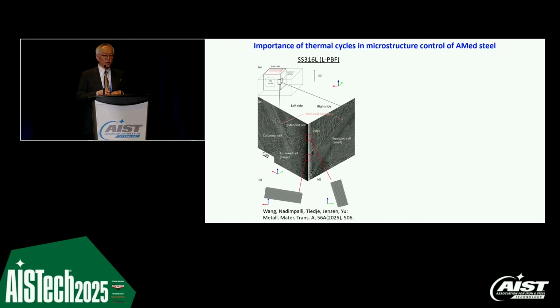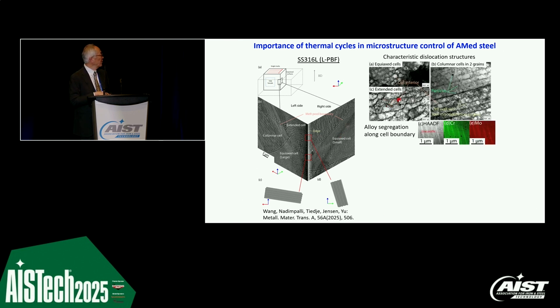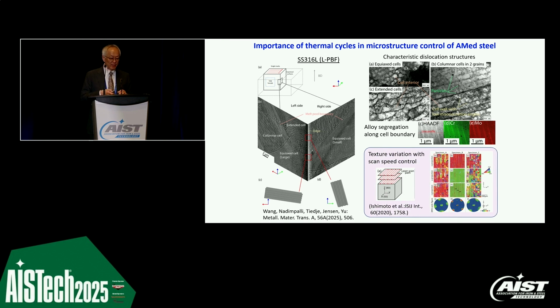This is one example with austenitic stainless steel, where we have a very nicely aligned structure during laser powder bed fusion. And of course, we now know there are different characteristic dislocation structures as well as elemental segregation during these kinds of thermal cycles. I'd like to introduce one nice work done by Professor Nakano at Osaka University in Japan. They control the heating temperature, and they can actually change the texture by applying such reversion heating control. So it's obvious that controlled heating is very important for additive manufactured steel too.